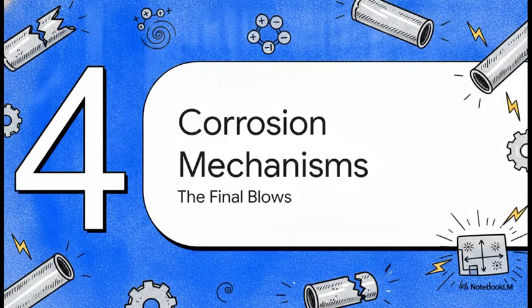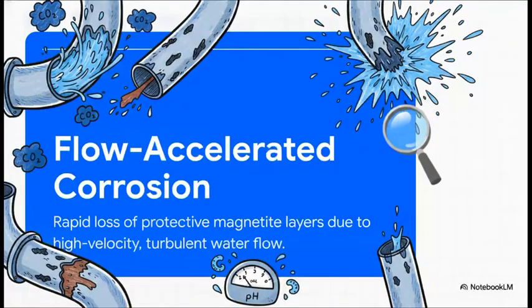Section 4, HRSG corrosion mechanisms. Let's examine the final blows. First up is flow-accelerated corrosion, or FAC for short. This one primarily goes after low-pressure economizer elbows, piping, and headers.